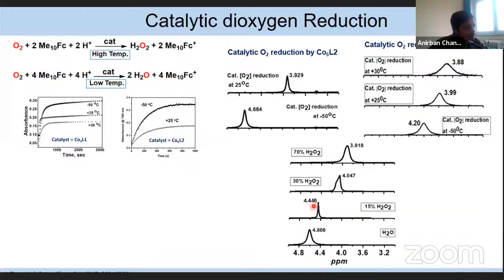to 4.4 to 4.0 to 3.9. That means with the amount of hydrogen peroxide, the signal is shifted. And then I tested the reaction mixture after the catalysis for tetranuclear cobalt complex at minus 50 degrees centigrade. I saw the signal at 4.20 ppm, and this 4.20 is in between the 4.04, which is for 30% hydrogen peroxide, and 4.44, which is around the 15% hydrogen peroxide.